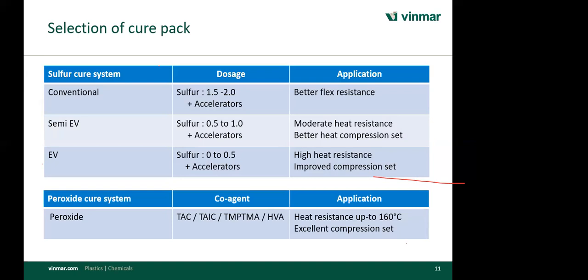So how can we avoid blooming issue in EPDM components? Ma'am, I already discussed blooming. Please add PEG 2 to 3 phr maximum, depending on your filler loading. If your filler loading is more, add more PEG. Second, you can add TMQ or TDQ 0.5 to 1 phr. Still, if you get some problems, you go for insoluble sulfur.